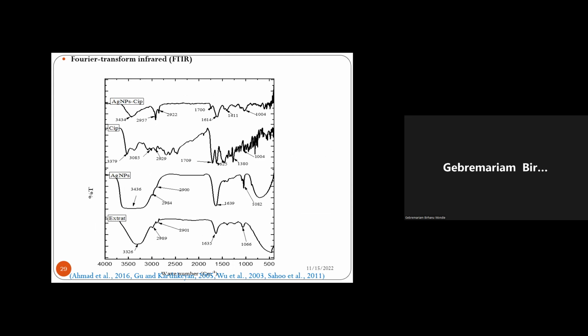As we see from this infrared spectrum, there is a variation between four of the spectra: the extract, silver nanoparticles, ciprofloxacin, and ciprofloxacin-loaded silver nanoparticles. So when you see the infrared spectrum of silver nanoparticles loaded with ciprofloxacin, it shows clearly the loading of ciprofloxacin, because its spectrum is completely different from ciprofloxacin, silver nanoparticles, and the extract. The major peaks of both silver nanoparticles and ciprofloxacin appeared in the ciprofloxacin-loaded silver nanoparticles, further confirming successful loading.